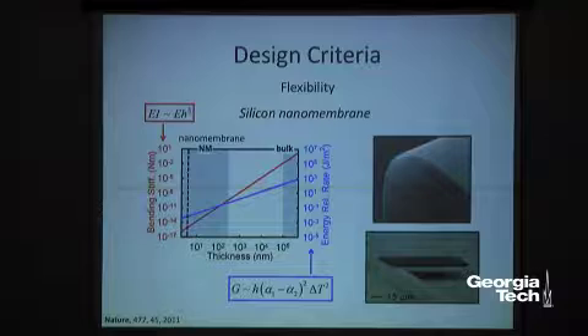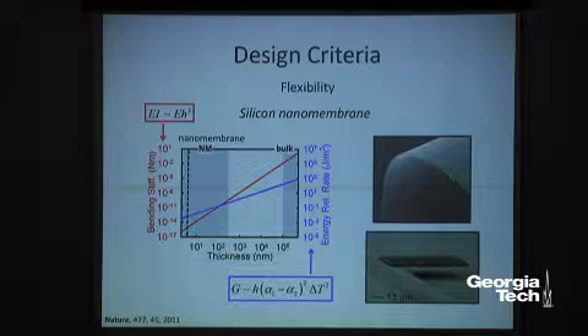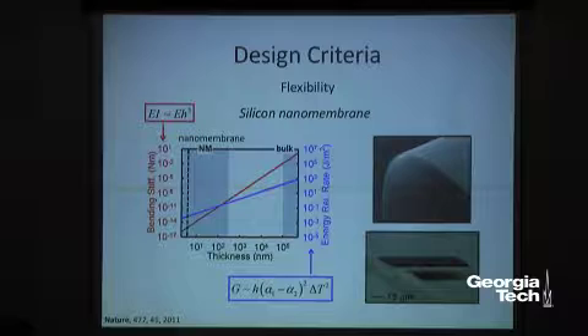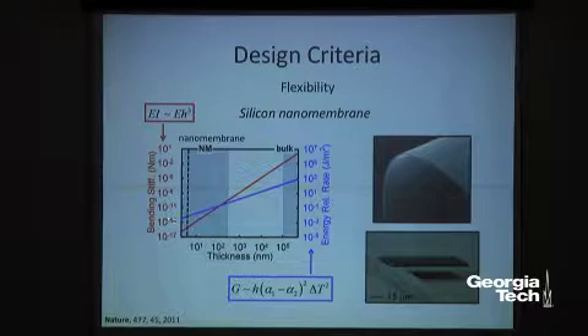So like this silicon, you can make gold, silver, or tin, copper flexible by just reducing the thickness. Right? So that's the key to make this flexible electronics with these core materials that we normally use for electronics. At the same time, once you reduce the thickness, you can get another advantage, which is about this crack propagation. If you put two materials together, then crack propagation happens from the energy relation. But if you reduce the thickness, then you can get that benefit as well by reducing this energy release rate.